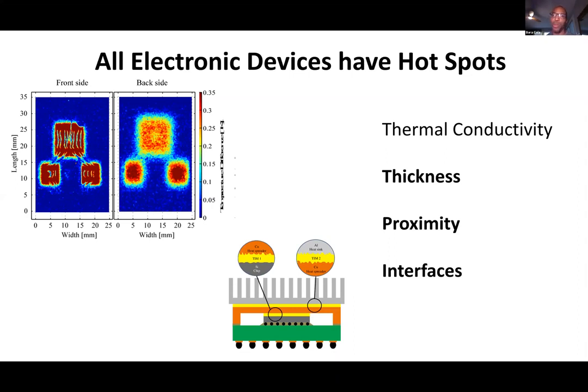And I'll give a practical example. When you look at graphite, which has been something that has been in Samsung Galaxy phones, iPhones, and tablets, oftentimes in industry, people have to use adhesives to laminate 2 or 3 layers of graphite together to get practical performance. Mainly because you need to have some cross-sectional thickness to the spreading material in order to be able to get the heat out effectively for the system. So, as we develop these 2D materials, the way we layer them and integrate them and how it preserves the thermal conductivity and system level properties are just as important as having very pure high conductivity materials.